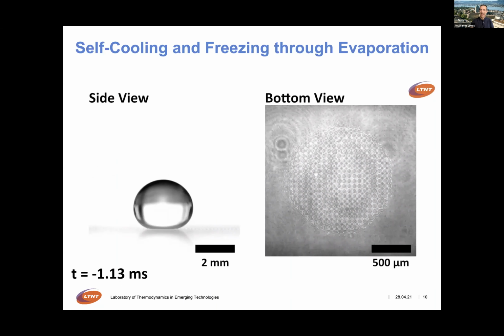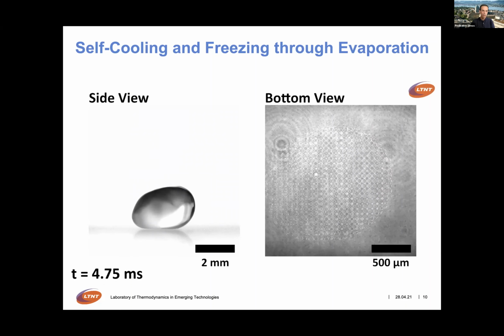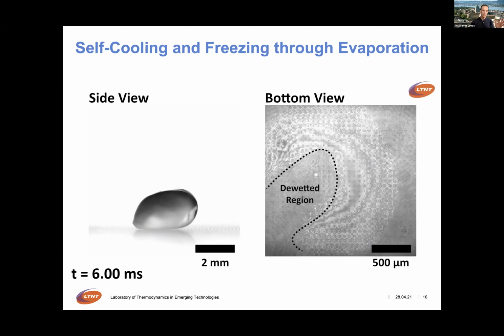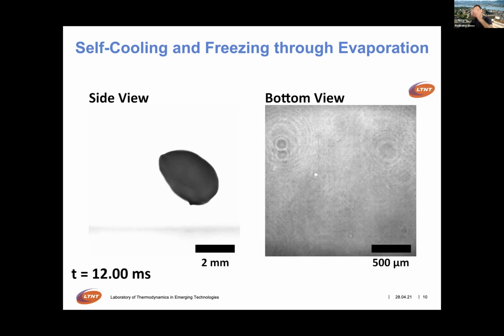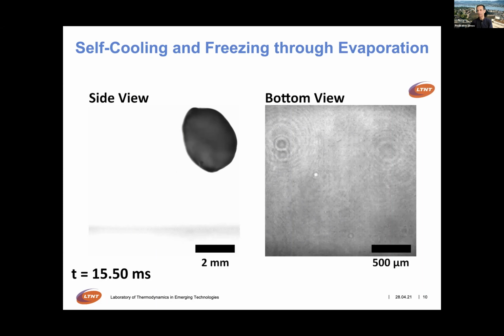So you see the droplet, and here under the droplet, the force is very high, it deforms the droplet. And then, of course, you see the de-wetting that takes place because the shell is asymmetric and kicks the droplet away. So with that, we were able to exploit this first level of the first phase of nucleation.